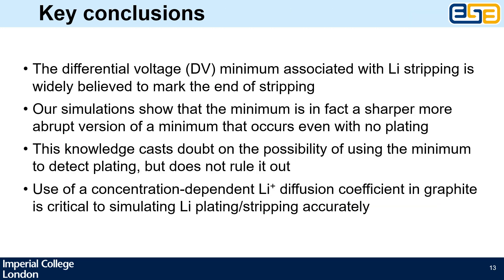In conclusion, the differential voltage minimum was previously widely believed to mark the end of stripping, but our simulations showed that the minimum is in fact a sharper, more abrupt version of a minimum that occurs anyway. This throws serious doubt on the possibility of using the differential voltage minimum to detect plating, but does not rule it out altogether. Finally, using concentration-dependent diffusion coefficients is critical to simulating plating and stripping correctly. Thank you very much.